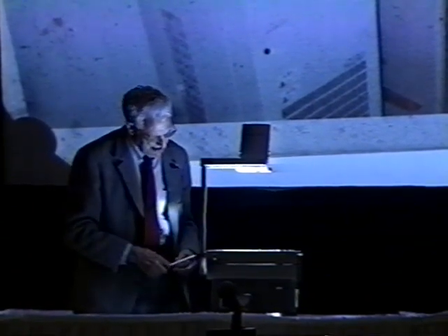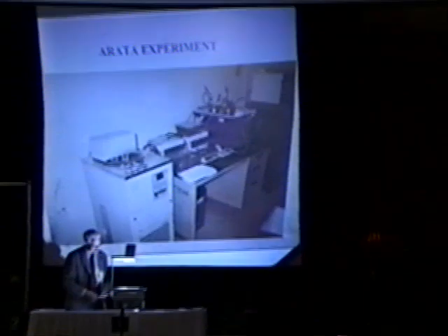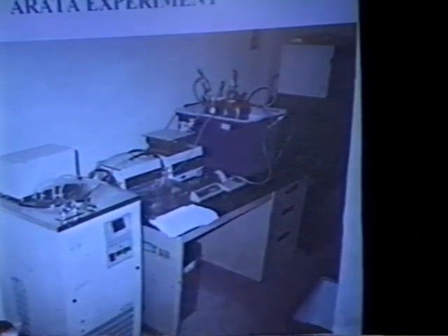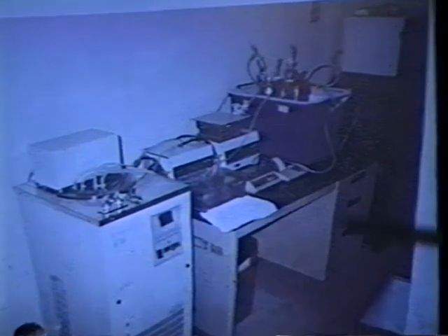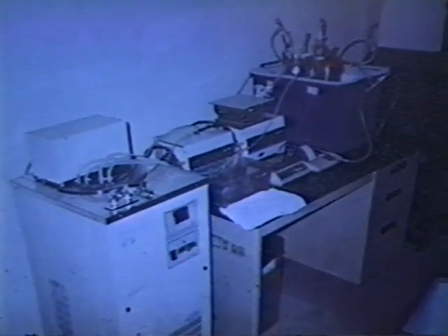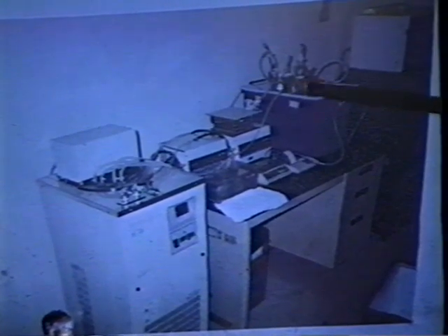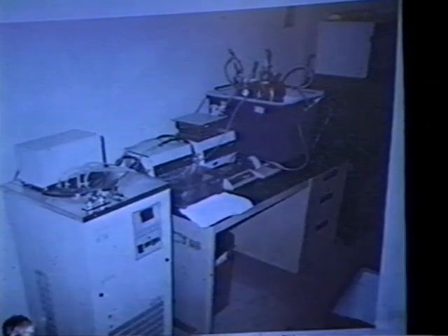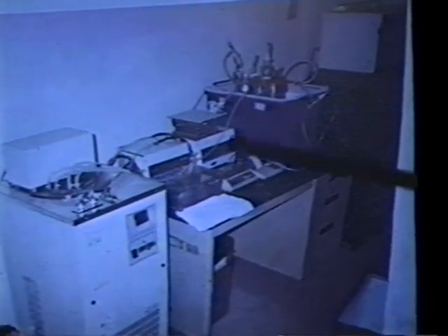Basically, the heat measurements, I'm just going to show you one heat measurement. Arata and Zhang do their calorimetry over in this area where they have a constant temperature bath, constant displacement pumps. They're set up to study cells at one time. The cells are in dewars here. They redundantly measure the temperature of the water that's flowing into these dewars, into a loop inside the dewars and coming out, and calculate the heat from the normal mass flow relationship. So that's in one